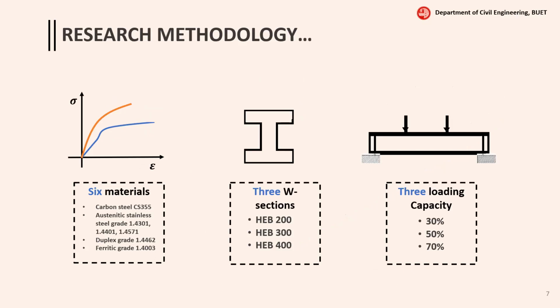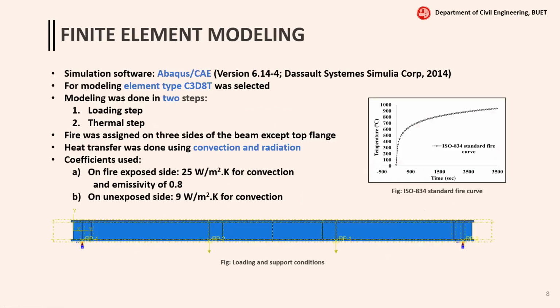In our study, we use 6 types of materials, including 1 grade of carbon steel, CS355, and 5 grades of stainless steels. 3 beam sections were taken, and 3 loading capacities were applied to each of them. The finite element modeling was done using Abaqus CAE version 6.14.4, selecting element type C3D8T, which is suitable for thermal displacement analysis. Modeling was done in 2 steps, loading and thermal step. In the loading step, at first the structure was loaded and then fire load was applied on all 3 sides except the top surface, using fire curve ISO 834 as the firing temperature. The fire loads were applied using convection and radiation with the appropriate coefficients.